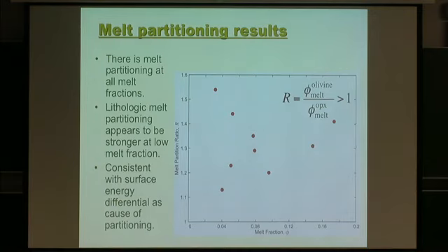But then you plot them against the melt fraction, and this is what you get. Given the range of the jumps, one thing that comes up is, yes, there is more melt associated with olivine than the OPX. I think that's robust. And if you really want me to put a number on how much more, I would put it somewhere around 1.4, 1.3. That's the ratio. This is all with 40% OPX. We now have another suite that has 20% OPX.